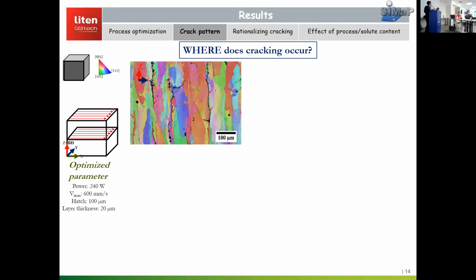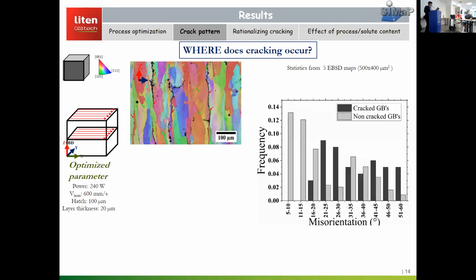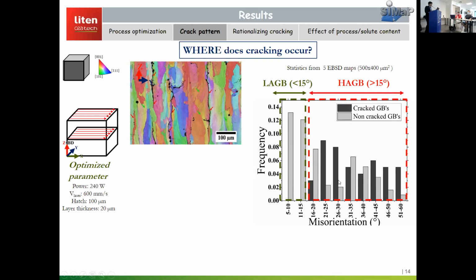If we look at the statistics of grain boundaries based on their misorientation, what does it give us? The low angle grain boundaries, which are less than 15 degrees of misorientation, were consistently non-cracking. But if we look at high angle grain boundaries, for instance the dark bars here, those are cracked grain boundaries. Most of the grain boundaries were high angle grain boundaries. But there are also a few high angle grain boundaries which were non-cracking in nature.